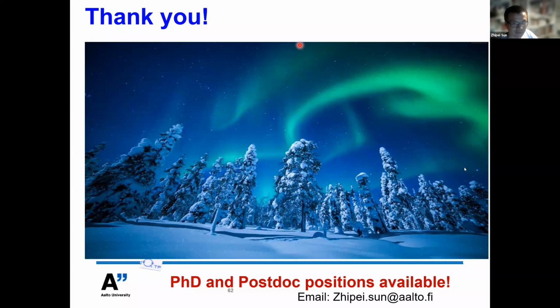Yes, so we're working with Professor Javier Abajo from ICFO in Spain. What he did is extract the band structures of four different materials and try to calculate this nonlinear response with first-principles methods. However, for MoS2, the difference between the theoretical and experimental results is much, much larger than for the other three. So most likely, and we agree with you, this is because of the subband structure. But we haven't been able to fully confirm this by linking the experimental and theoretical results. Right, right. Thank you.